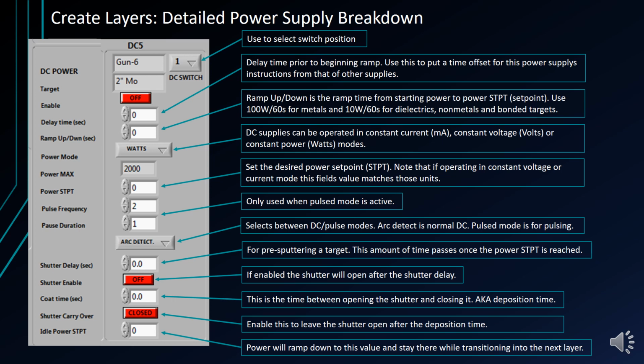The idle set point power is the power that this will ramp down to once the coat time is over. So if you were to set it at 30 watts and you were at 100 watts and your ramp time were 60 seconds, then once the shutter closes, it would ramp down from 100 watts to 30 watts over 60 seconds, for example.